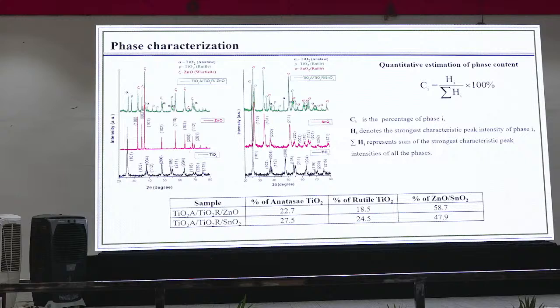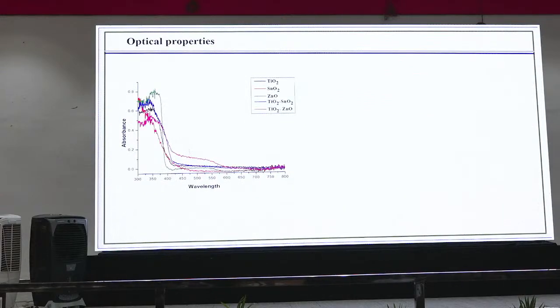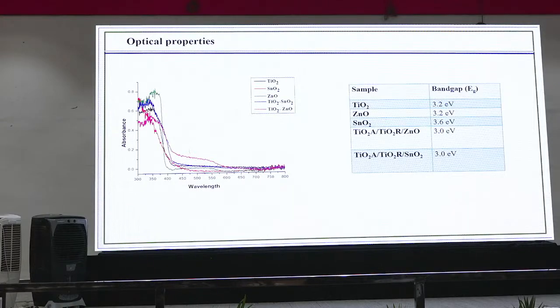When I cross checked, I didn't get it. Mine was 50% anatase and 50% rutile. So I was not able to get that particular composition. But we have developed some material, so we wanted to make use of it. Then as usual, since we are working in photocatalysis, we check the band gap. When we checked the absorbance, we got visible light absorbance, then we calculated the band gap. The band gap is slightly shifted to the visible region from the UV region.